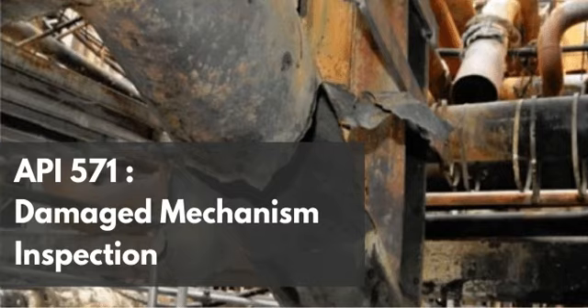Yes. The physics of ultrasonics are essential here. You are pulsing high-frequency sound waves into the steel at an angle. When those sound waves hit the highly branched intergranular faces of the carbonate crack, they reflect back to the transducer. And the software interprets that. Exactly. By analyzing the time of flight and the amplitude of the returning signals, PAUT can build a highly accurate volumetric profile of how deeply the crack network has penetrated the pipe wall.